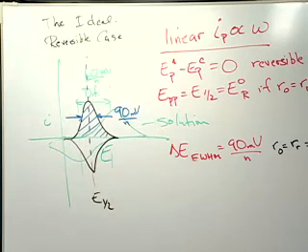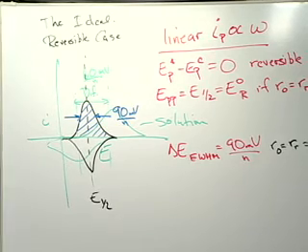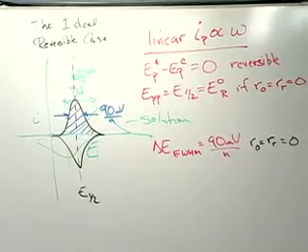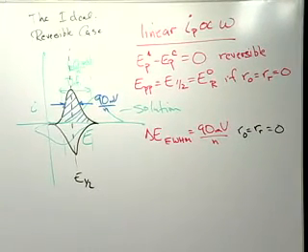So the first thing that this lets me do is figure out whether or not the molecule is on the surface. I attempt to put it on the surface. Did I succeed? And it's the linear scan rate dependence. That's probably the best indicator of that. But of course, the peaks lining up with each other is another good indicator. Like solution cyclic voltammetry, though, the peaks may not exactly line up.